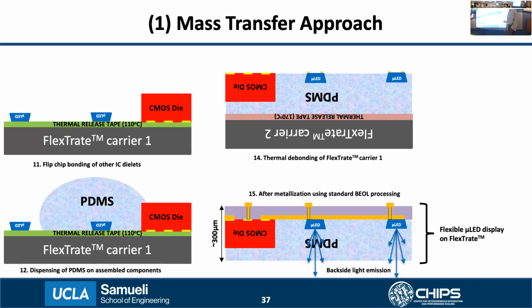Yeah, so this particular process is a standard fan-out process, so essentially any kind of molding compound could be used. But we would prefer to use an elastomeric material such as PDMS, which is a silicone. The reason is an issue called die shift that happens during the compression molding of the molding compound over the devices. When you compression mold the molding compound, it exerts drag forces on the devices, causing them to shift in position, and that limits your achievable interconnect pitches and so on.